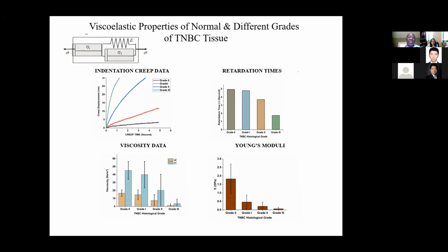And so if you now extract for these the viscoelastic parameters for those different types of tissue, what you basically find is that the viscosity is highest for the normal tissue, and then reduces with increasing progression of grade from grade 1 to grade 2 to grade 3. And similarly, the moduli also reduce significantly from normal tissue to grade 1 to grade 2 to grade 3. And so with these kinds of results, you can see also that the changes as you go from one grade to the other can be more than the range in the data. So again, giving us a little bit of confidence that these kinds of viscoelastic measurements can now be used to track the evolution of the viscoelastic properties as you go from no tumor to grade 1 to grade 2 to grade 3 breast cancer.